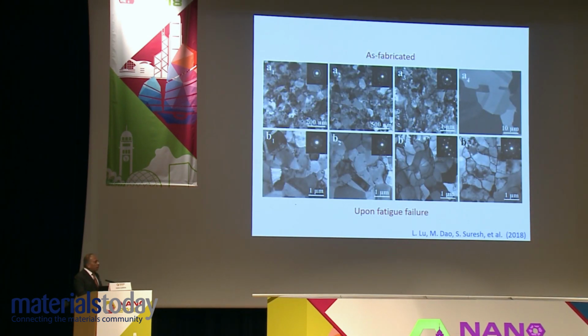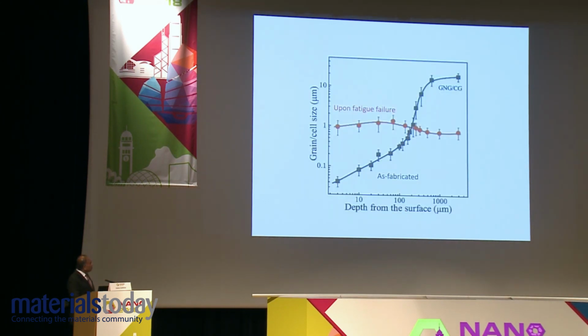In the as fabricated condition, you get nanoscale. The scale here is nanometers. You get nanoscale microstructure. If you go deep into the material, you get microcrystalline material. But after some period of cycling, the microstructure homogenizes, and as a result, you get nearly uniform microstructure of roughly comparable grain size or cell size through the thickness of the material. And that leads to some really unique fatigue properties.